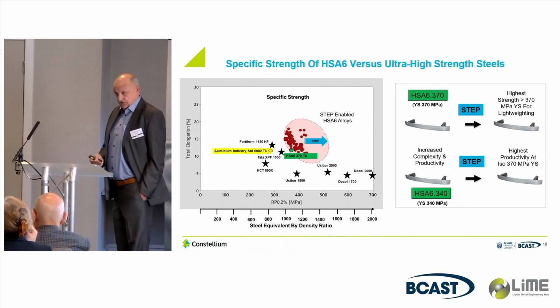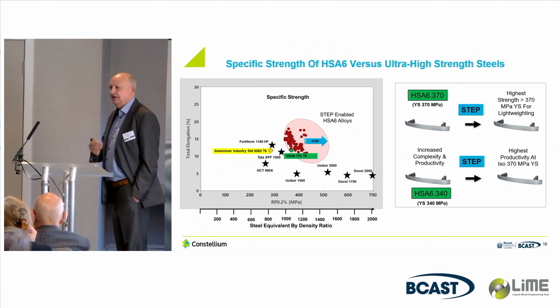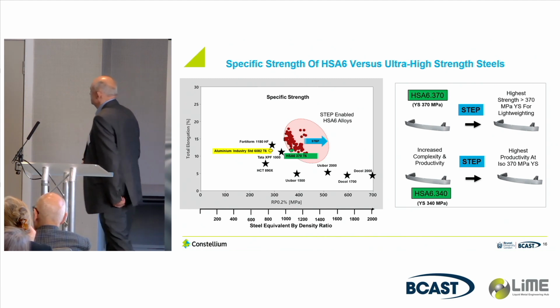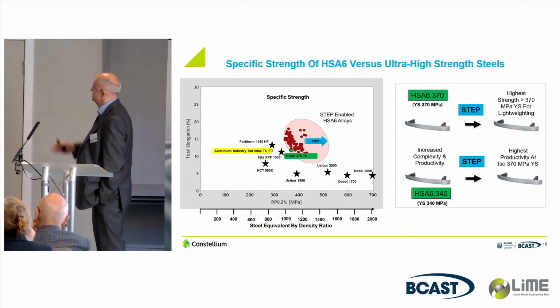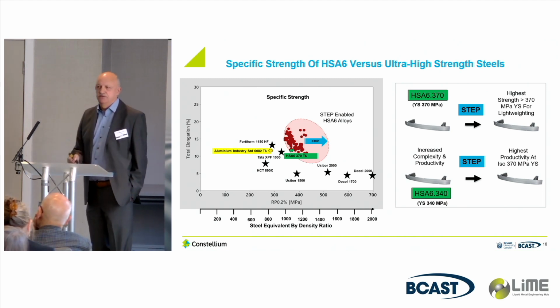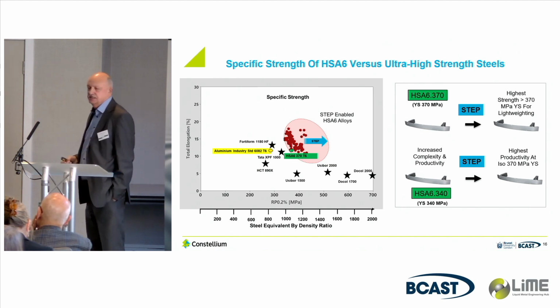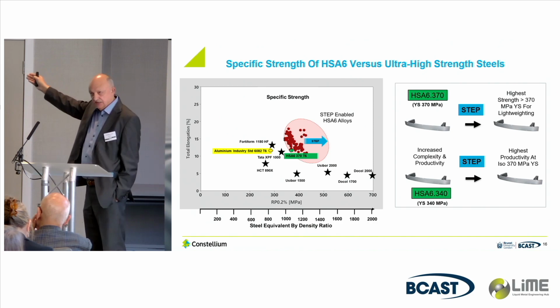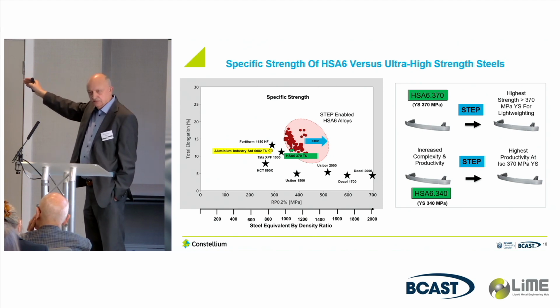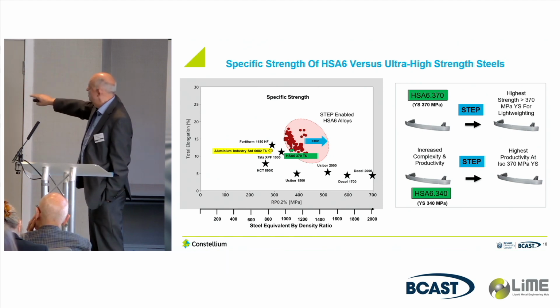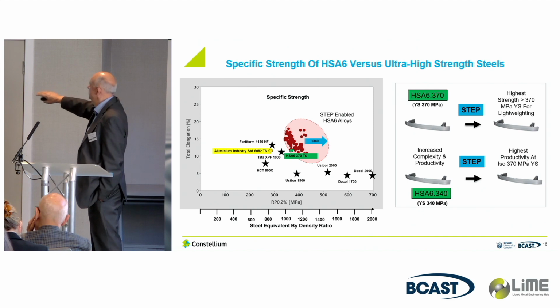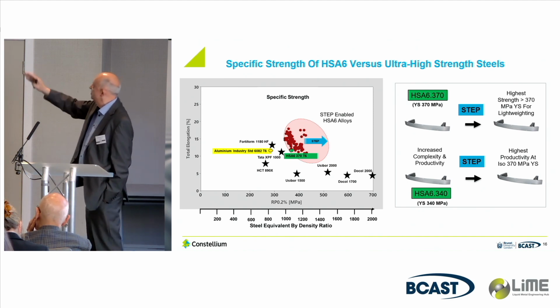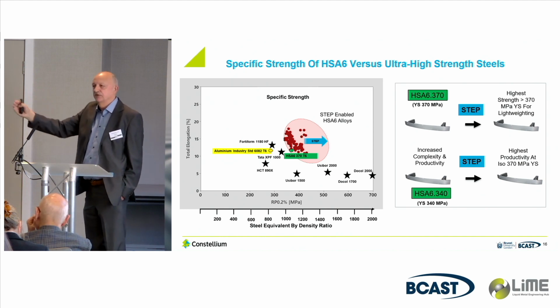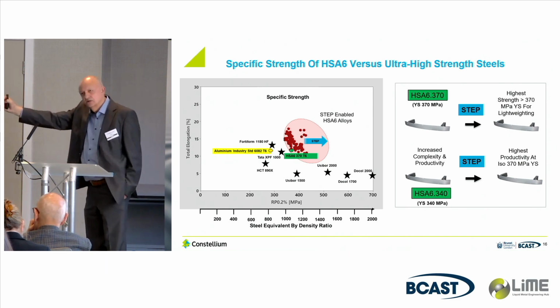That allows us to use less material, but we've also got to maintain that ductility so that we can keep that crash performance. And we've basically set ourselves two targets. One is how far we can physically take that strength. How high can we go? We currently have HSA6 with a 370 proof. Now that is a 6000 series alloy, and we've deliberately chosen 6000 alloys because they're highly tolerant to recycling. So that's one. The other one is we use a slightly softer material, and in this case, how can we still maintain a high level of productivity and then use the STEP process to increase the strength, perhaps not to the ultimate, but to a higher value.